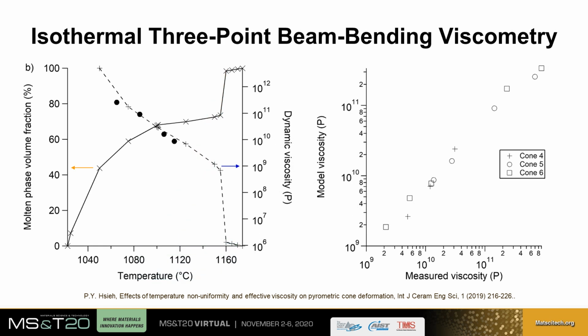In 1968, Thomson published a doctoral dissertation on the thermal deformation of glass crystal systems while a student at The Ohio State University. Thomson was concurrently a research engineer at the Wharton Ceramic Foundation and wished to measure the effective viscosity of pyrometric cones at high temperatures. He did so by constructing a 3-point beam-bending viscometer, with which he measured the effective viscosity of cones 4, 5, and 6 as a function of temperature.